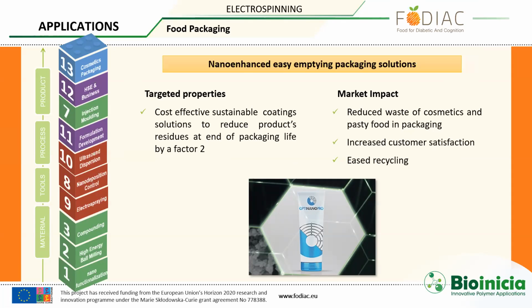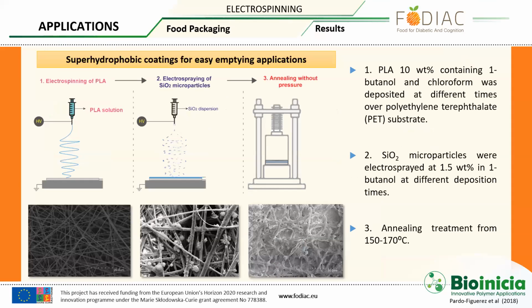So with this coating, you could have the whole material going down, and you could use it all. We would save money, and the customer would be happier because the whole product is being used up. And this would ease the recyclability of the tube because there won't be much material left there, and overall it would reduce waste in both the packaging and the product. We did this with a multi-step process where we apply a layer of electrospinning, a layer of electrospraying, and then a thermal annealing without pressure, sorry. This thermal treatment was just to stick the two layers together, because one of the main issues with these coatings is that they peel off quite easily.